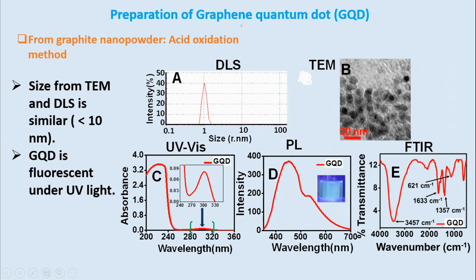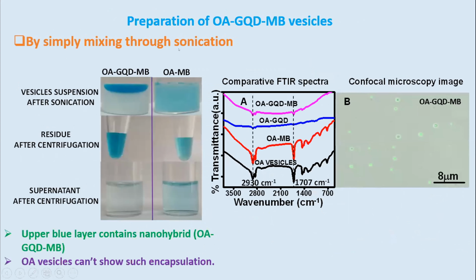And finally, I also prepared graphene quantum dot from a reported method. It's an acid oxidation method, and you can see the spherical structure of graphene quantum dot. Here we also use graphite nanopowder. The quantum dots were fluorescent in nature. Then I attached graphene quantum dot and oleic acid vesicles by simply mixing and sonication. And you can see here the upper layer is the composite system containing the model drug.